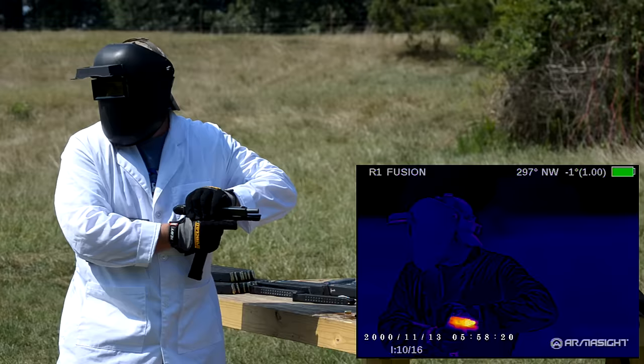The trigger did begin to melt. You have the small pin on the Glock here on the top side, which is a metal pin. So you had the recoil block, and this pin worked as a giant heat sink and transferred a bunch of heat to the trigger axis pin and the trigger itself, and the trigger melted. All right, and what it did is it melted and it swelled, and it's touching the side of the frame and it's not allowing it to reset.